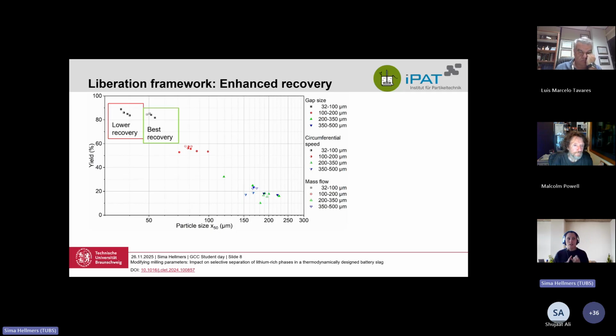To look at this, the first step was the flotation, and then based on what was in the flotated part, that was the target. Our first target was lithium aluminate. So this one was done and then added to the leaching. The best size that we had was under 100 micrometer, and they had a very high yield. That means that a lot of material was flotated.